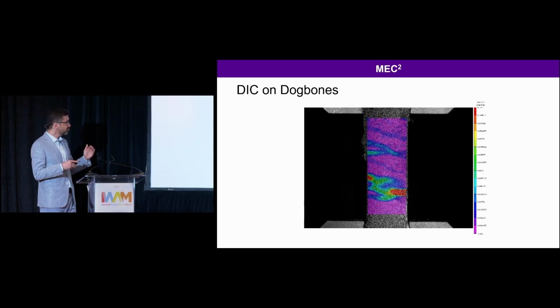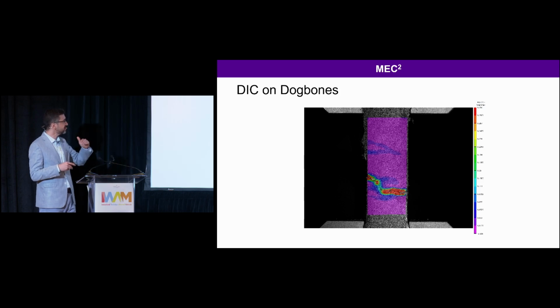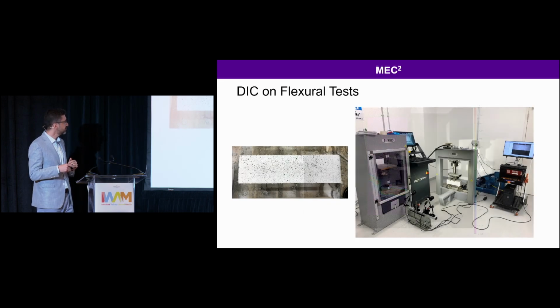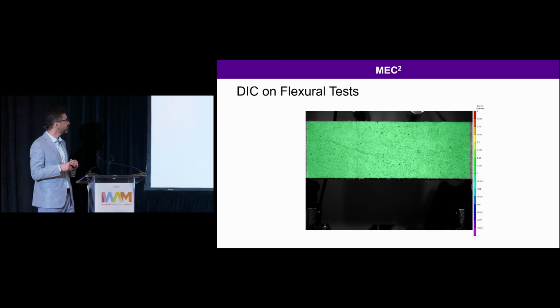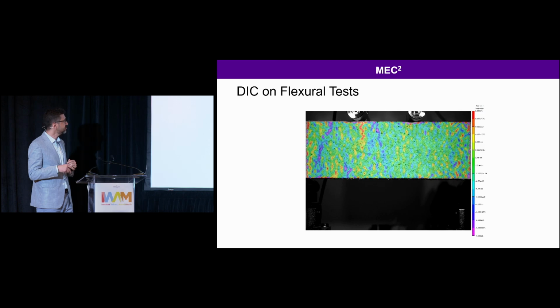There, we are able to see the energy dissipation through cracks, but our goal is to increase these cracks throughout the matrix. And then this is the test that we have done for the 4-point bending test. Again, once it is loaded, we can see the cracks, also stress and strain development. And what we'd like to see is the red color changes distributed towards the bulk faces.